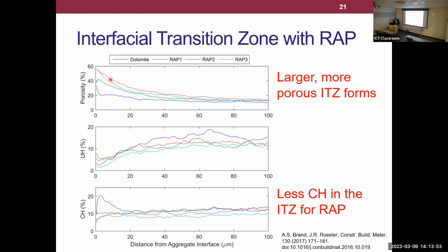Right, we look at 3 different RAP samples, okay, and we can clearly see there's a lot more porosity for our 3 RAP samples relative to our control. So we have a larger, more porous ITZ surrounding all of our RAP particles. That basically means we have a lot more porosity in our concrete, right? Pores don't carry weight, right? So that's why we're reducing our modulus, really. It's because we now have a lot more porosity.